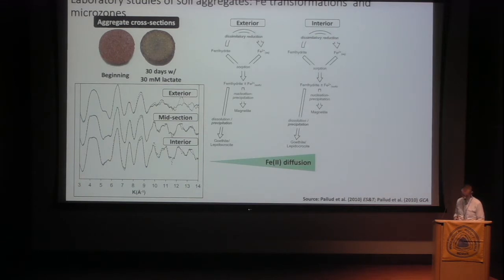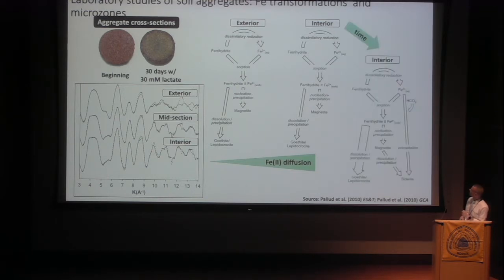And they could say something about what is happening to the mineralogy as a function of time and space as iron is diffusing from the inside out, resulting in secondary precipitation of goethite and lepidocrocite. Over time, though, what's happening in the interior is starting to change as there is a buildup of reactive species, including the potential for the precipitation of siderite, but a greater degree of goethite and lepidocrocite.